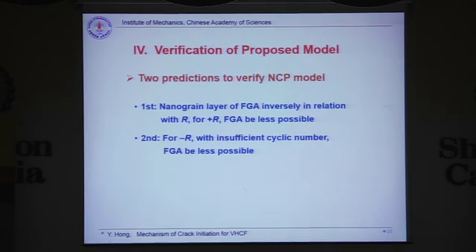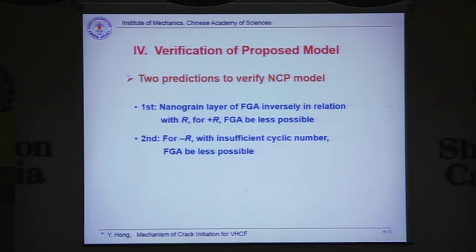To verify this, we have two predictions. For the first prediction, because this process is due to the contacting of the crack surfaces, we may predict that for a positive stress ratio, there will be less action of the crack closure effect. So this kind of nanograin layer on fracture surfaces will be less likely.